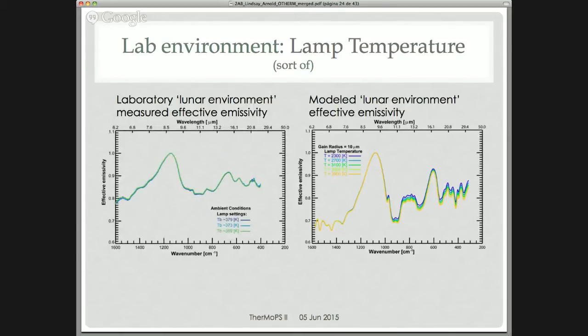And here, though, in the lab, instead of varying the lamp temperature, we just change the lamp setting until it gives us a certain brightness temperature at a wavelength that's somewhat featureless. So that's probably why there's less variation in our laboratory spectrum than in the modeled one, because for the model, like I said, I decided on quite a large range of lamp temperatures. But even so, for the model, again, the CF doesn't change too much when you change this parameter. And in the lab, even in the Reststrahlen bands, it doesn't seem to matter too much.